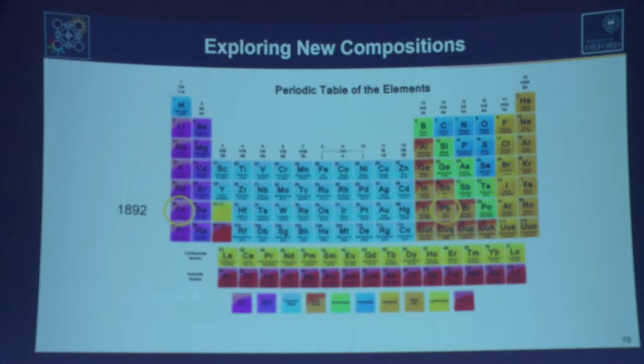So moving on, the first tin or lead halide perovskite discovered was cesium lead triiodide. That one works quite well as a solar cell, but there are some issues. Cesium is slightly too small for that compound to be stable in this three-dimensional perovskite structure that we want, so actually we want a slightly larger ion. If francium wasn't radioactive, we'd really like to use it, but it's not going to be suitable for widespread deployment.